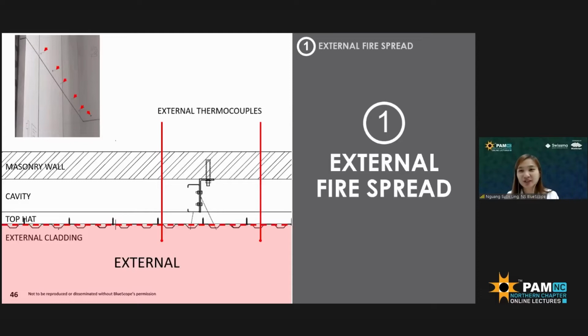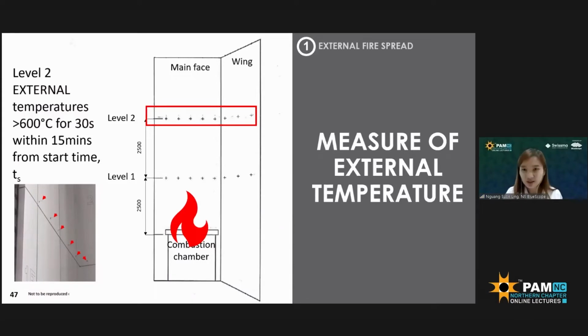The first criteria is about the external fire spread, and it will be measured based on the level 2 external thermocouples, meaning using all these thermocouples. In order for the cladding to pass, the external surface should not allow the fire spread coming from the combustion chamber, which simulates the fire coming out from the window. To be more precise, all the external thermocouples at level 2 should not have a continuous temperature reading of more than 600 degrees C for 30 seconds within 15 minutes from the start time.